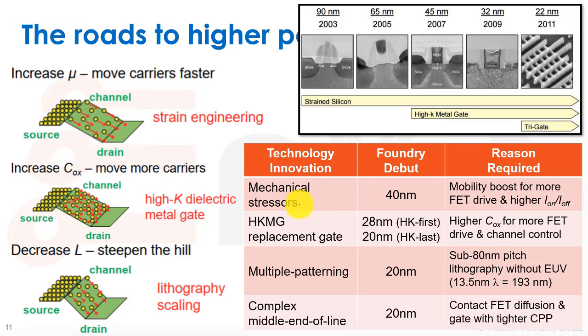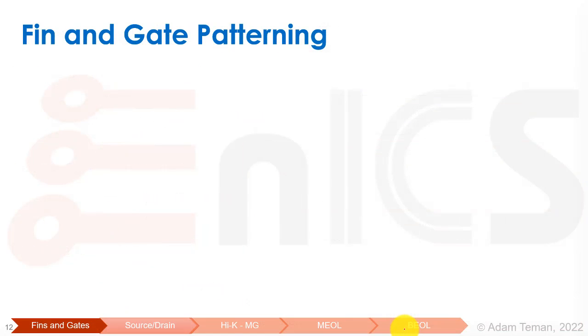And really, so we use mechanical stressors in all of the foundries around 40 nanometers. We used high K metal gate and replacement gate around 20, 28 nanometers. Multiple patterning used around 20 nanometers, and complex middle end of the line around 20 nanometers. And we'll be discussing all those things now. So we have a bunch of things that we need to go over, and we'll start with how we pattern the fins and the gates.